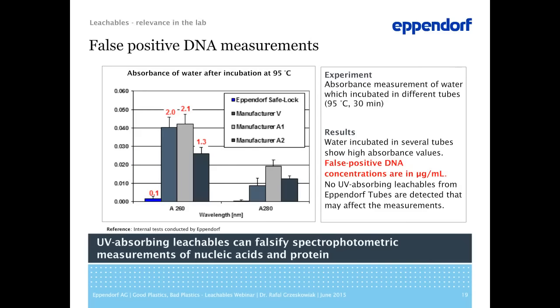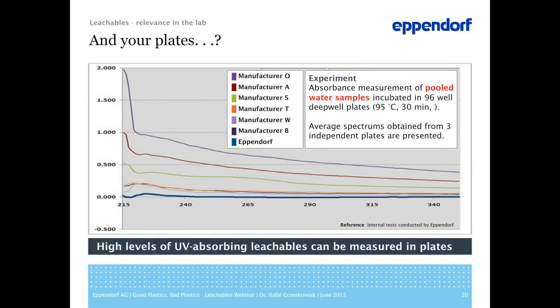Even after relatively short incubation times, the amount of false DNA, so to say, was reaching over 2 micrograms per milliliter, which is considered pretty high and sufficient for most assays where DNA is used as a template. Well, in this case, we didn't do any of these assays, as it surely might be just frustrating. The samples also showed high readings at 280 nanometers, which is typically used to quantify protein, and in this case also leading to false positive quantification. And well, let me conclude here. UV absorbing leachables can falsify spectrophotometric measurements of nucleic acids and protein. I'm slowly losing my voice.